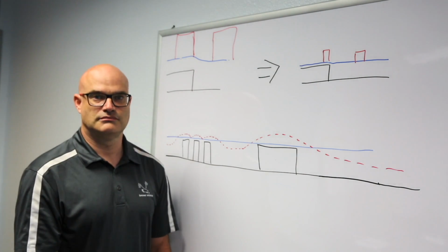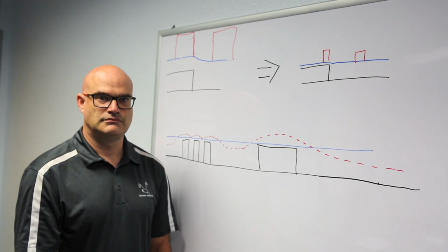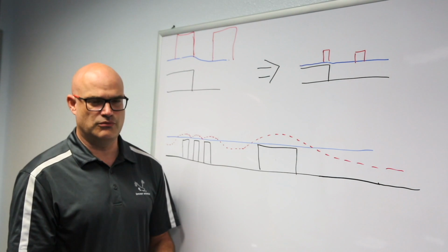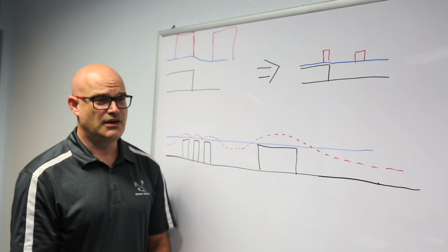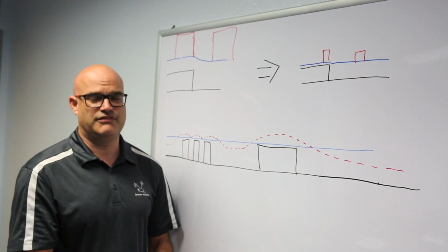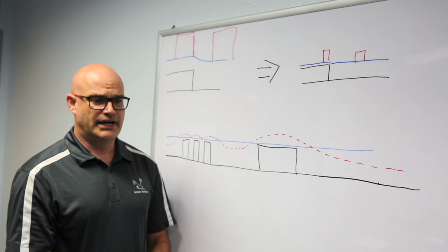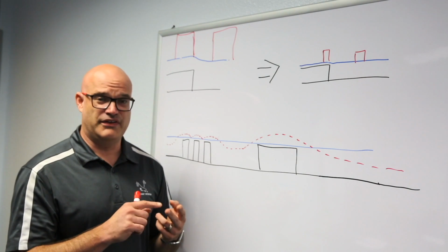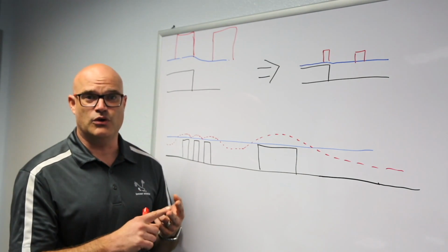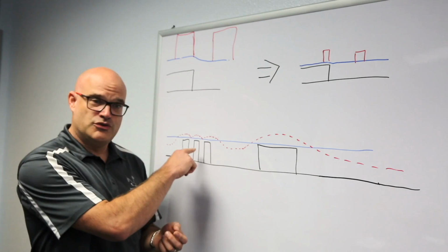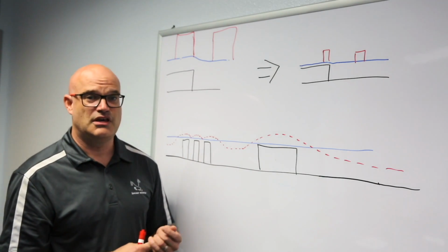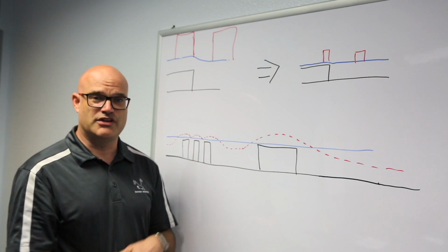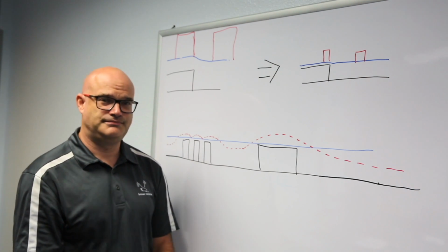We're going deep into material science here. What sort of chemistry challenges are you running into? Yeah. To make a material that can withstand these temperatures for a long period of time, you really look at a small subset of the chemistries available in the world. You're talking about polymers that aren't very soluble in a lot of cases, and they also don't want to flow. So to get a material to go into a small hole can be very, very challenging. And when they don't want to flow, they also don't want to planarize. So you have to look at some really special chemistries to make that happen.